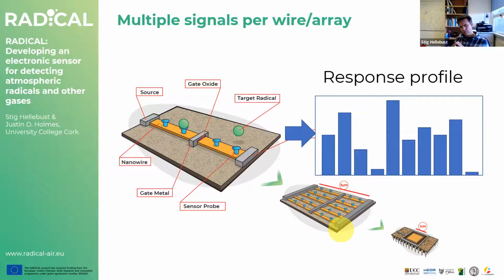Some of them depend directly on the surface chemistry, some of them depend directly on the other parameters, and hopefully they'll all tell us something about the target species. So we have something like this, a profile of different signal responses for each wire. These wires, of course, you can reproduce, you can make them identical, so you can pack a lot of them in. And the idea then is that you can make the surface chemistry different on every one of them. So you get not just one of these profiles, but as many as you can put onto the chip.